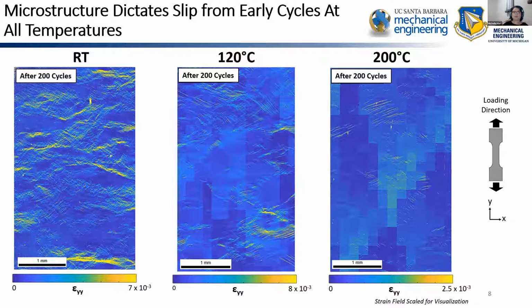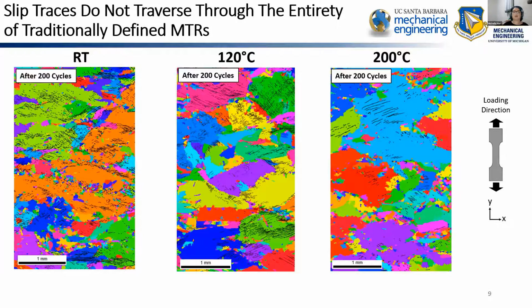And so then the question is, what about that microstructure drives this process? And so we want to think about this in terms of our microtextured regions that we were talking about before, where this map here has taken the orientation mapping from the EBSD and run it through a Dream3D pipeline with very standard microtextured region segmentation processes. And then we've also taken those strain maps and been able to segment out those individual slip traces and then overlaid them on top of that MTR map, shown here as those black lines.